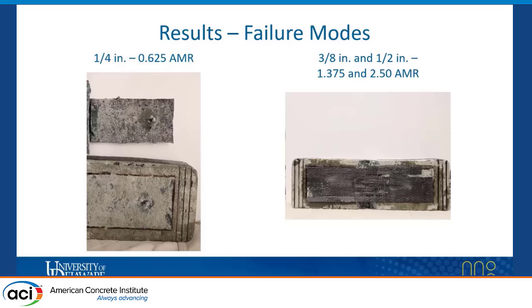In addition to this, the quarter-inch anchors failed primarily by anchor rupture, whereas the 3/8 inch and the half-inch groups failed primarily by strip fracture following ACP. The belief for the anchor rupture of the quarter-inch group is that it is due to the decrease in interlaminar shear strength between the fiber anchor and the composite layer, as well as the insufficient AMR for developing the strip stresses.